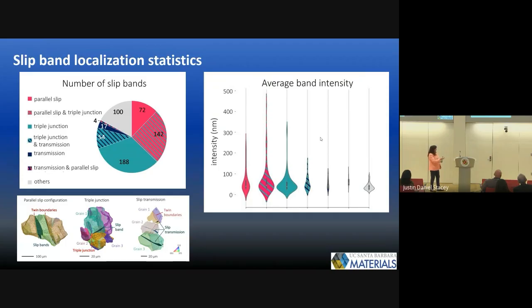an annealing twin which intersects a triple junction. So it's sort of like the superposition of two things that will give you a stress tensor. And this is more consistent with the volume of material that you're encountering. So is the microcrack initiated at the triple junctions? Yeah. Is that where failure occurs?